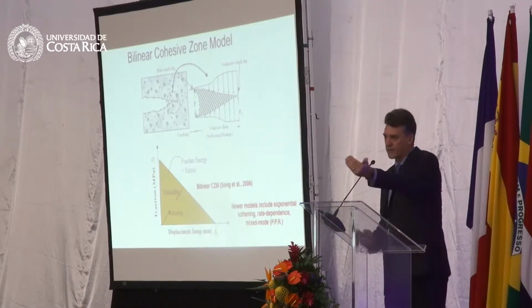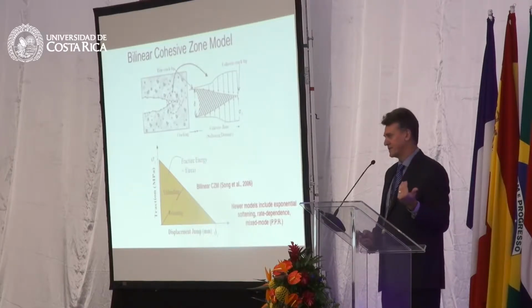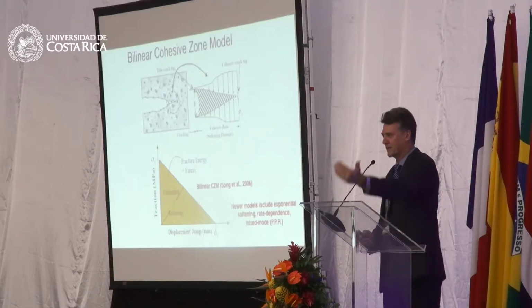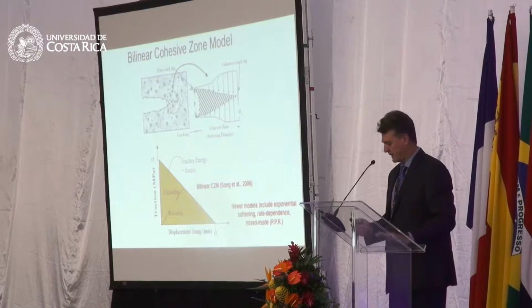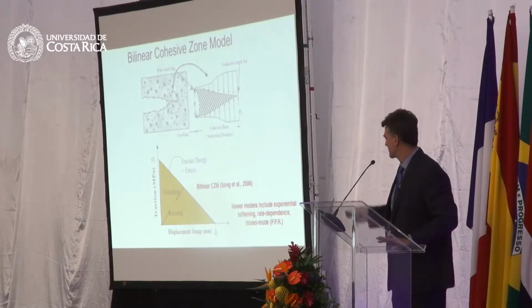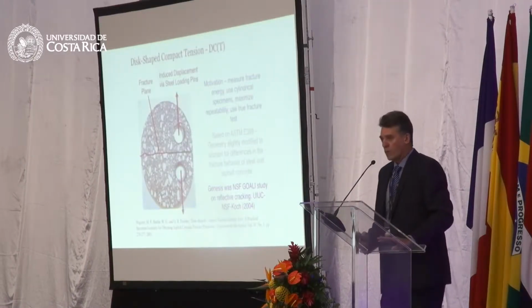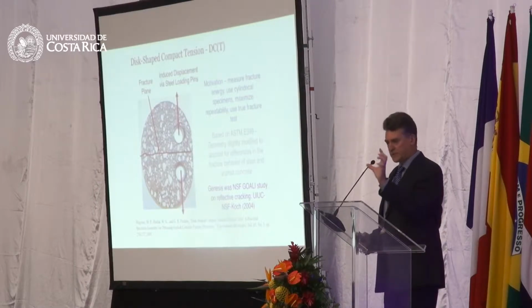Some of the new tests we've developed have really characterized the material in the post-peak, and from there you can back up and develop a fracture-resistant pavement. You have to be able to predict the cracking and then back up and make your design stop short.